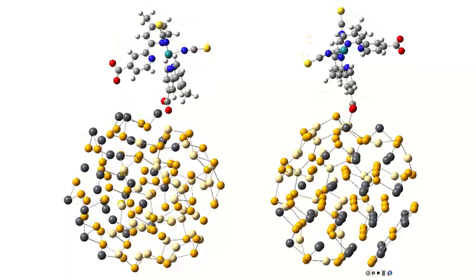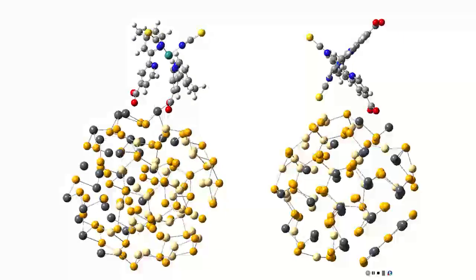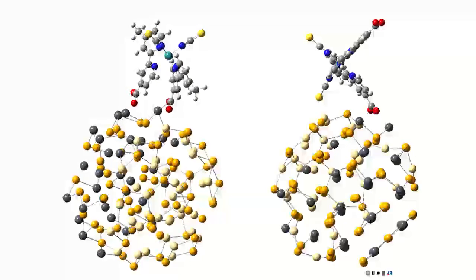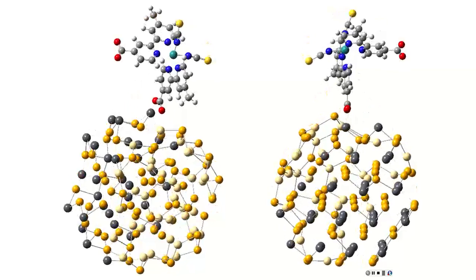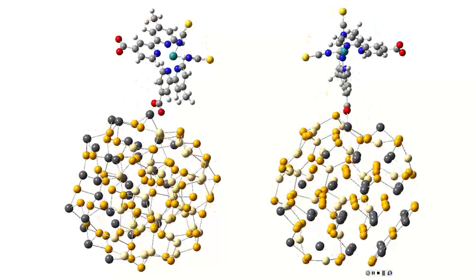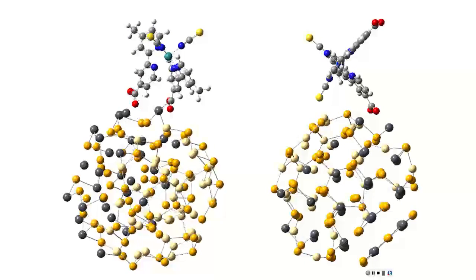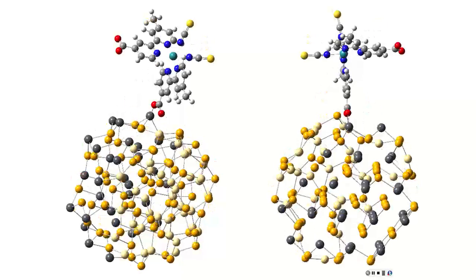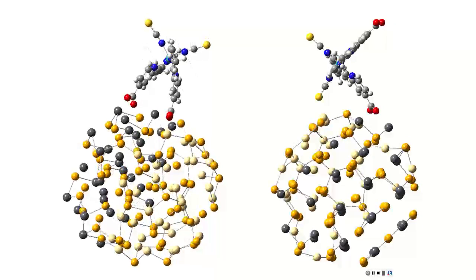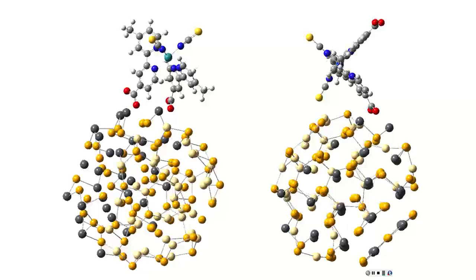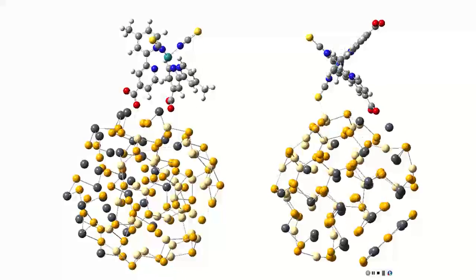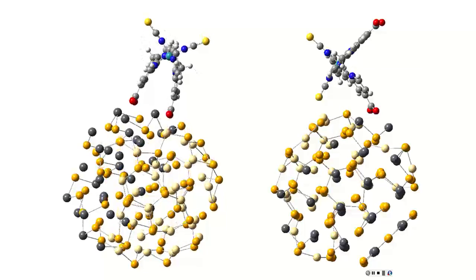This is a very polar molecule. We calculated the dipole of something more than 100 debye for these molecules. For cadmium selenide it is around 20 for the lead surface dipole, and for lead it's something like 5 or 10, I don't remember. So it's a huge dipole, and when you interact with the surface, you drastically change the interaction and the dipole. That's why it's very natural to expect that even the atoms which are far away from the binding site should feel this and maybe rearrange, because you're really changing the dipole of the entire system.